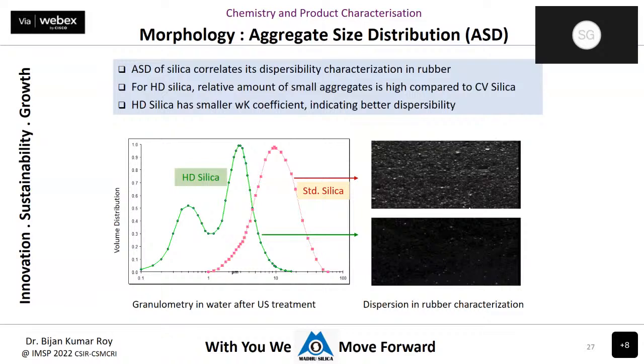So here we simulate this process. Silica under this sonication has disintegrated. The higher the disintegration, the lower the particle size, and the better the dispersibility of that particular silica. So you can see in the rubber mixed compound for standard silica, different white spots, which are silica. But when you see these highly dispersible silica rubber compounds, the black compound, you will not even find any white spot. So it is very highly dispersible.